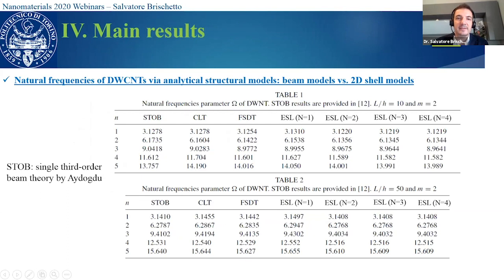So some results, in this case, we compare a beam model with some shell models. And this is a double-walled carbon nanotube analyzed by means of equivalent single-layer approach. Obviously, there is a difference between beam model and shell model when the carbon nanotube is short. This difference is smaller when the carbon nanotube is long.